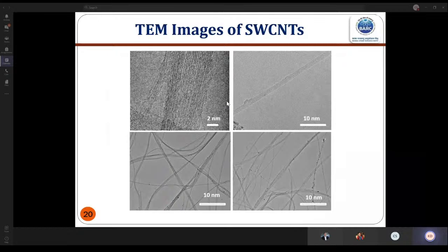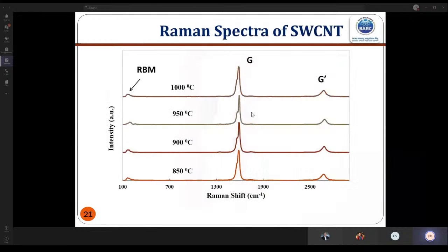As I told, we can also make single wall carbon nanotube. In single wall carbon nanotube you get only one wall, but they come in bunches. Because of very high surface energy, they try to make bundles, so we always get them in bundle form. And if we see the Raman spectra, you can see here the D peak is missing. D is due to defects, so generally in single wall that peak is missing. We get another peak called RBM, the radial breathing mode peak. This is a very characteristic peak for the single wall carbon nanotube, and we can actually calculate the diameter by analyzing this peak.